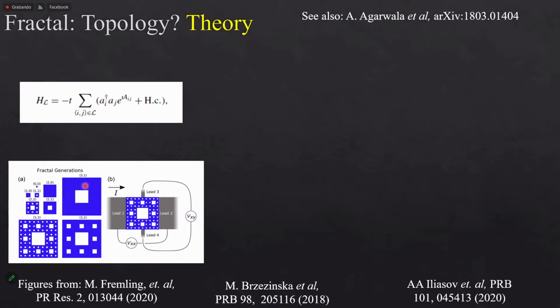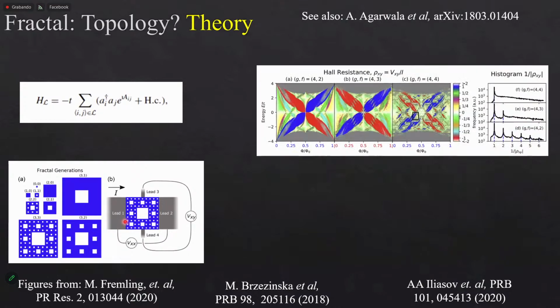And basically what they did is that they took a square lattice, and then they were piercing holes in it, and tried to see whether you have the same phenomenology of the quantum Hall effect. So they did that both computing this quantity that I showed you before, the Chern number, but also they did this experiment where you have a DC potential, you induce a current, and you measure the transverse voltage. So basically, looking at the Hall effect.